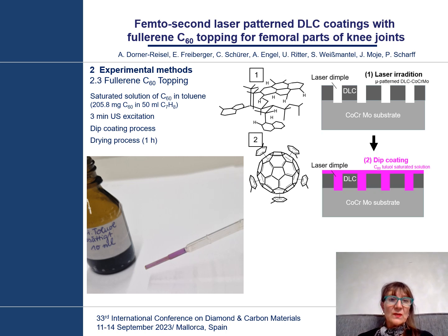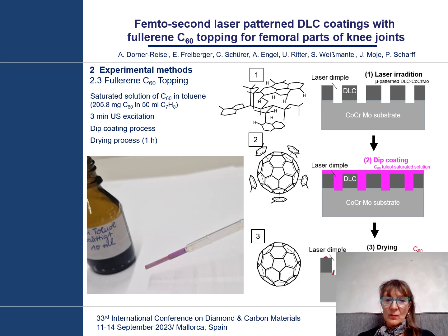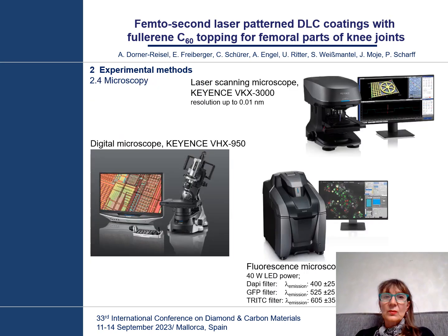The coating process was performed with a saturated solution of C60 in toluene. After drying, the molecules of C60 form needle-like crystals on top of the laser-patterned surface. In our study, the surfaces were investigated by different microscopic techniques like digital microscopy, laser scanning microscopy, or fluorescence microscopy.